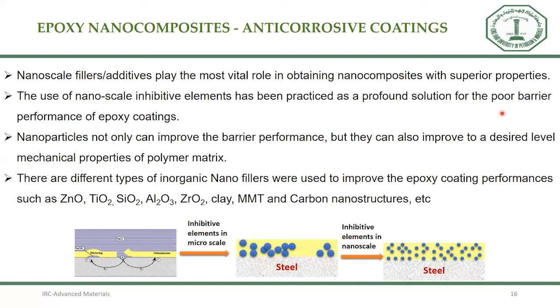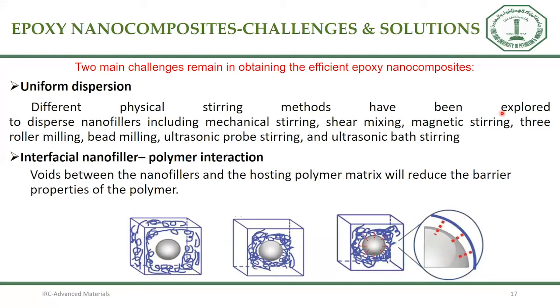The main challenge in the development of epoxy nanocomposites is uniform dispersion. We need to ensure homogeneous dispersion of these nanomaterials inside the polymer matrix, which can be done using different techniques like mechanical stirring, ultrasonic probe stirring, and ultrasonic bath stirring.